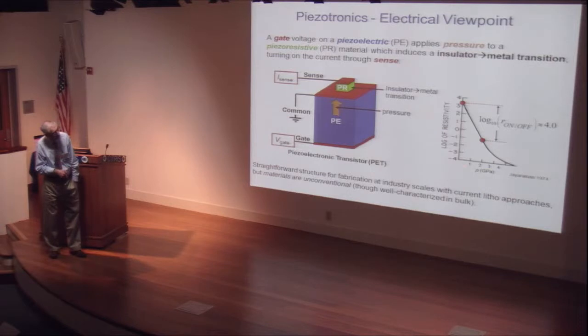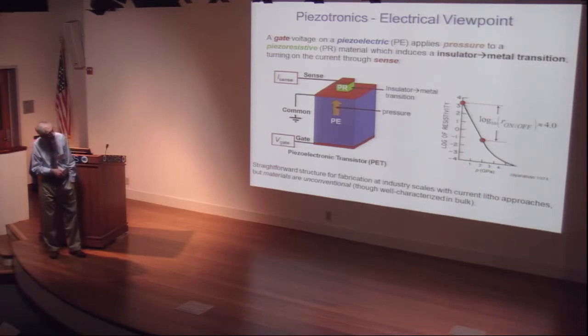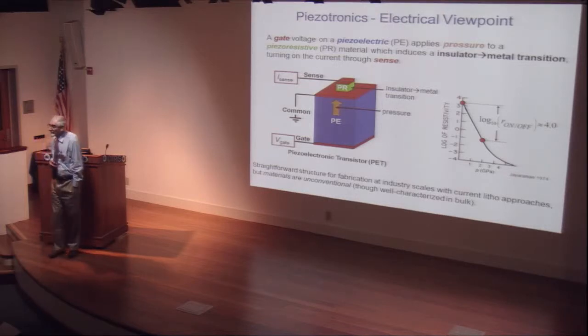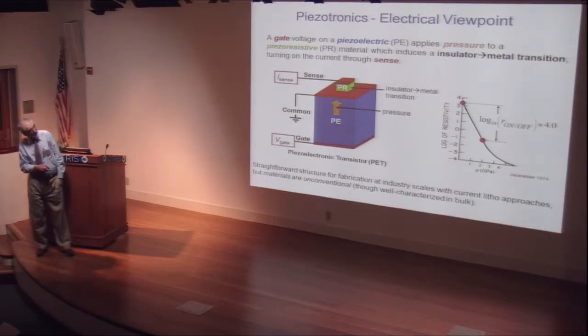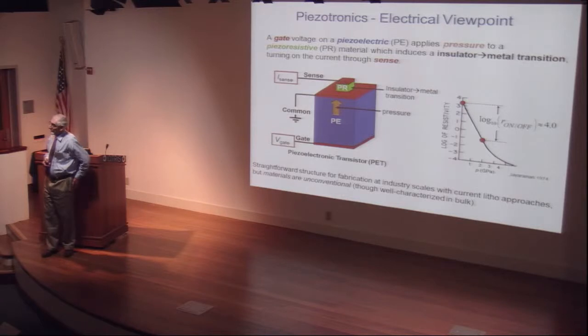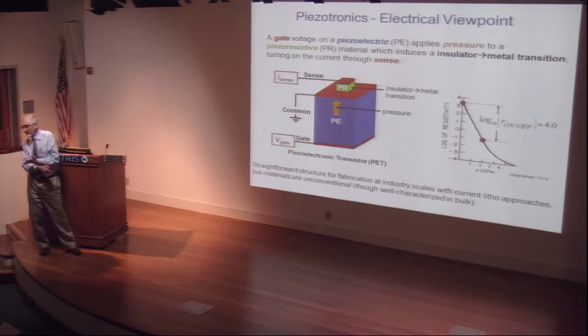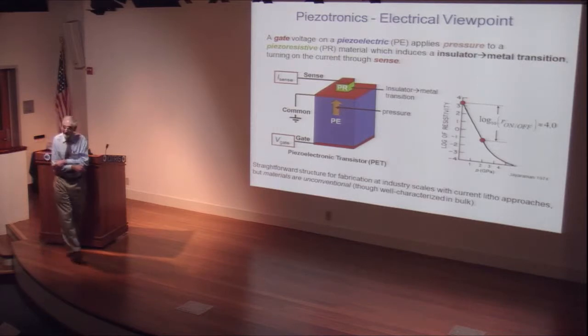This is a picture of the log conductivity versus pressure of such a material, samarium monosulfide. This is part of some very fine Bell Labs work in the 70s. You see that it can change by seven orders of magnitude with about three and a half gigapascal of pressure. We will be using part of that range, about four orders, in the device.